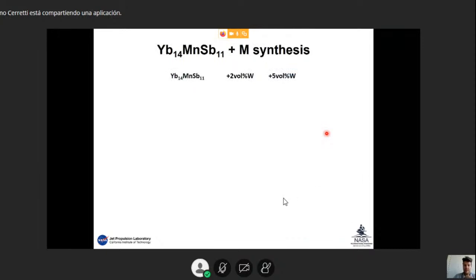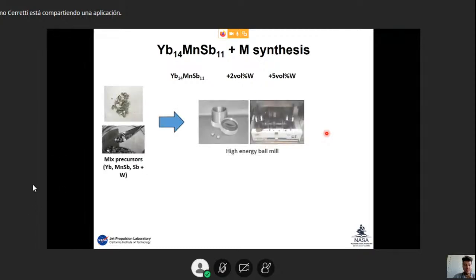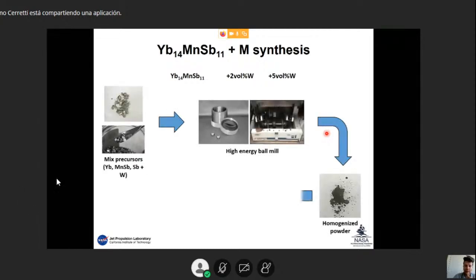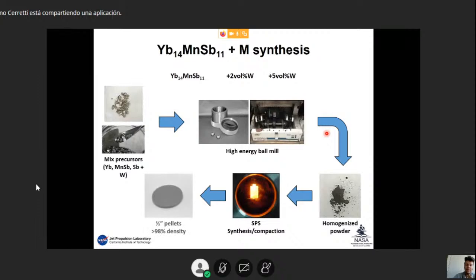So in this case, since I thought lower inclusions should guarantee the same results, I just analyzed the 2 and the 5 volume percent. The synthesis has been prepared in the same way. So we mix the materials, we shake them, we obtain powders, and then we sinter, and we get pellets with high densities that are used for characterization.